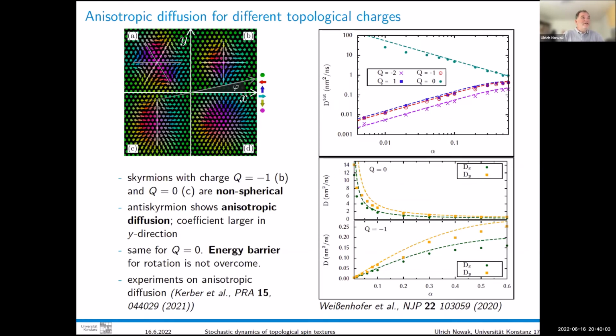So we can play around with this topological charge because, as I said, in our model system, this iron monolayer between platinum iridium and palladium, we can stabilize different topological structures, and that's what they are shown here again. So that is a normal skyrmion here, but there are also others like an anti-skyrmion or a structure with Q equal 2 here, and that is Q equal 0. That is topologically trivial because you could unwind this structure and could transform it continuously back to the ground state. It's not protected by topology, but it is stable in our model system here.